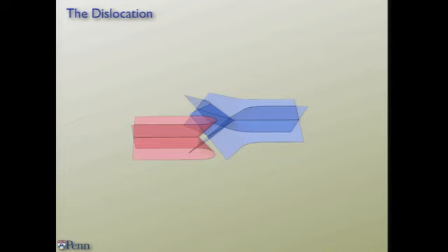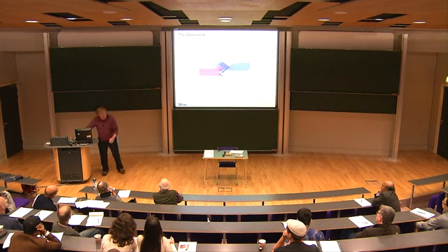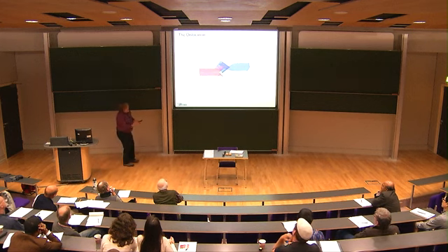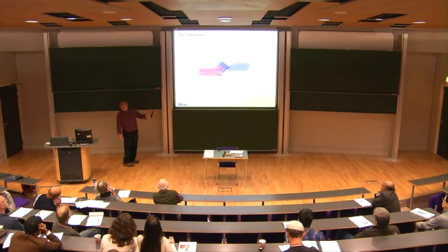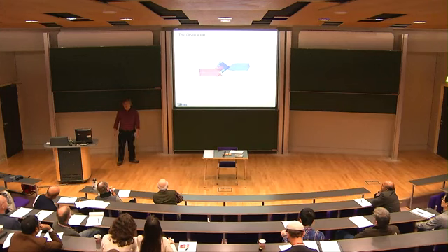There's an offset. And I told you that these lines where the surfaces cross are forced to be at certain heights, or your density wave is not well defined. That means I'm not allowed to deform things to move those crossing lines. The crossing lines can't move up and down. As soon as they move up and down, they mess everything up. So they have to stay where they are. So there's no way to get this red guy up half a spacing in this direction. And because of that, I can't turn a dislocation into a disclination.